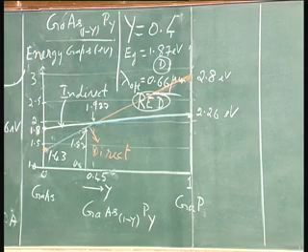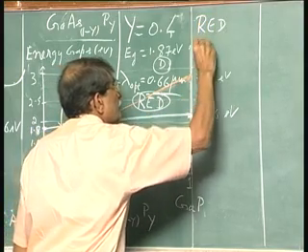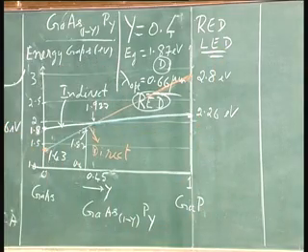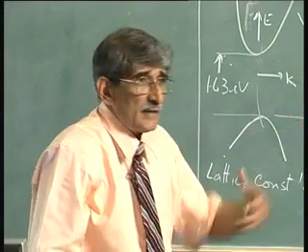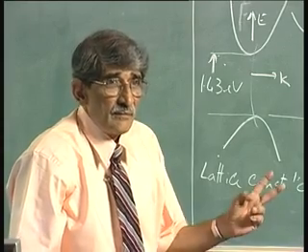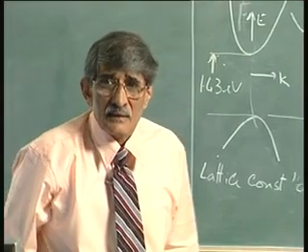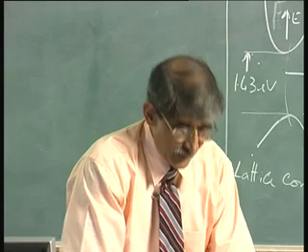So, you can make red LEDs, that is light emitting diode, LED, in case the abbreviation. So, you can make light emitting diodes with red emission by gallium arsenide phosphide with phosphorus mole fraction equal to 0.4, because that is very popular in desk calculators. Some of the calculators which people are using, that is also one very popular.